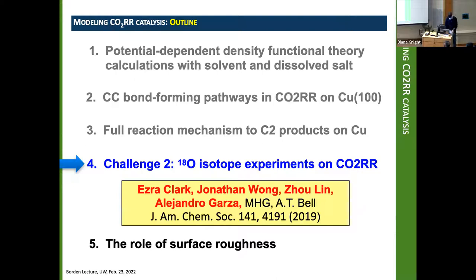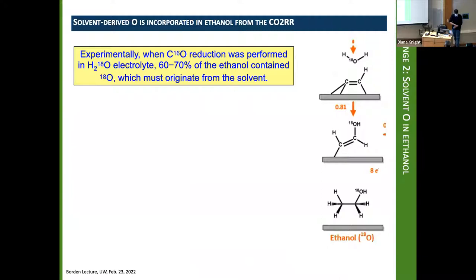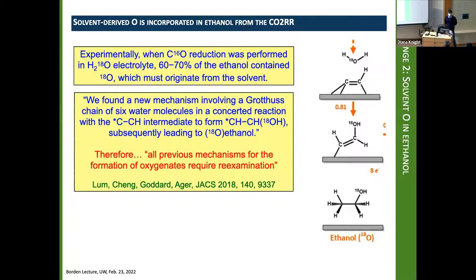A very good experimentalist at my institution, LBL, showed that when CO reduction was performed in water that used oxygen-18, something like two-thirds of the ethanol produced contained oxygen-18, which must then come from the solvent. And they then rounded up a theorist. They went to Caltech, where all the best theorists reside, and they reported as follows.